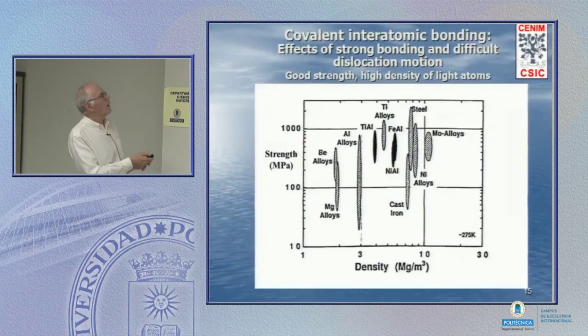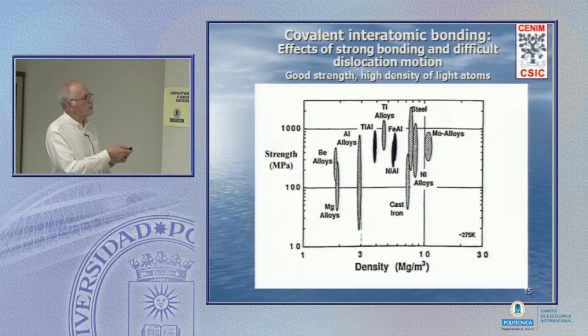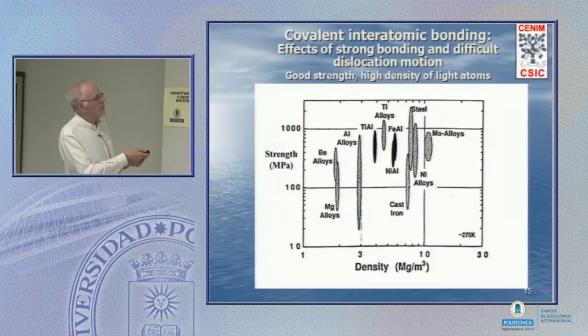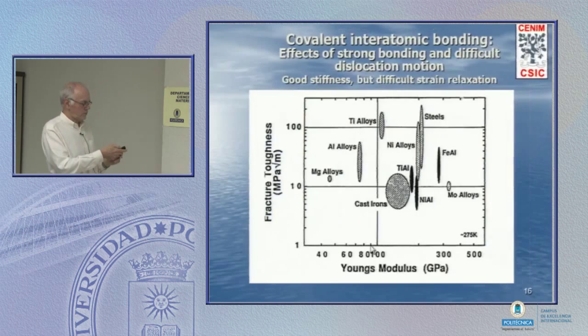So a couple of maps that show typical changes of properties because of these elastic and structural reasons. The strength and the density. Now here we've got steel, typical strength, typical density. Here's iron aluminide. I've put in a lot of aluminium. The density has come down a lot. The strength has not changed very much, actually. Nickel alloys and NiAl. Titanium alloys and TiAl. In very general terms, the strength has not changed very much here, but the density, yes, has reduced.